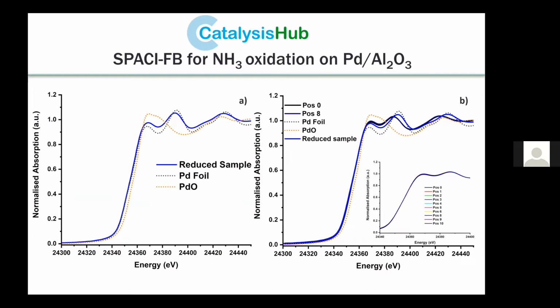We performed XAFS analysis on the catalyst after reaction in hydrogen, which you can see in A, and this is consistent with nanoparticulate palladium. However, after the introduction of the reaction mixture at 100 degrees, you can see in B, a predominant interstitial palladium nitride phase is formed, and is uniformly formed across the bed, as evidenced by the shift of the multiple scattering peak at 24,319 and 24,420.